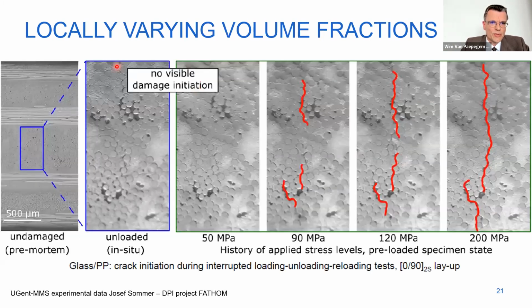But still a few more things about this microscale simulation, which is also about volume fraction. We assume a certain volume fraction in the representative volume element, but that is not always the local one which is driving the damage in reality. This can be the case for a perfect aerospace prepreg composite where the fibers are very uniformly distributed. But here you see a glass polypropylene thermoplastic composite, which is typically used for automotive applications. The fiber distribution in the thermoplastic tape is not so uniform. And there, if we increase the loading from left to right in transverse tension, you see that the cracks typically develop in the highly packed regions where the local volume fraction is a lot higher